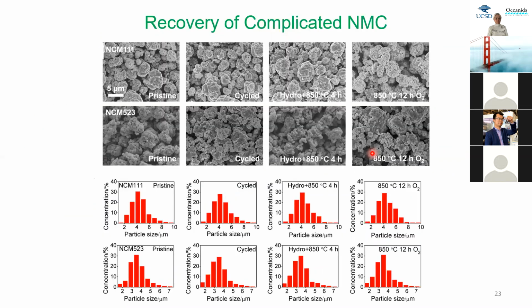So this is how the particles look like in terms of NCM 111. And this is 111, the first row. The second row is NCM 523. So they all look similar. So we want to compare how this particle material microstructure as well as morphology, particle size, and distribution look like after our entire process. So this is very crowded slides, but if you see there's very little difference. The truth is that indeed there's very little difference because the particle size distribution is similar. Okay, the morphology are similar.